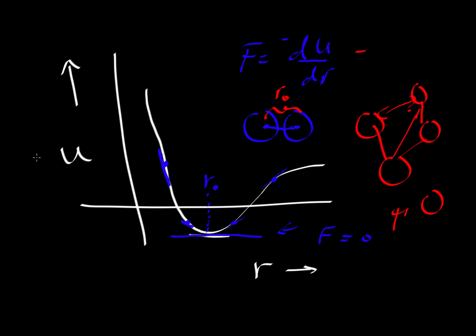Here's another thing. If this is an equilibrium distance, think of temperature as being a way to increase energy. If you have very cold temperatures, you would have some equilibrium distance here. But as this atom increases in temperature, let's have a very high temperature, where the average distance would now be the vibrations that would be bracketed by that curve. Notice that the average distance would actually be shifted to some value that is greater than R naught. As things get heated up, you should follow something of a curve, not a straight line, the equilibrium distance between the repulsive forces and the attractive forces, that midway point, would be shifted out to larger and larger values of R. So this is a way that we can explain so-called thermal expansion.